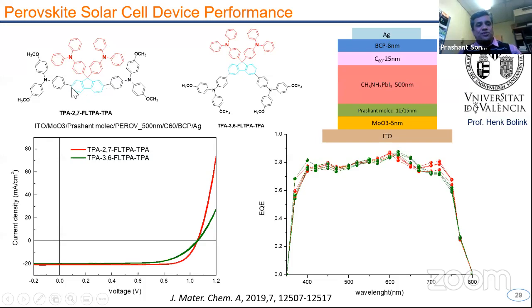Just by changing the position from 2,7 to 3,6, how does the performance change? That was one of the questions we asked ourselves. If we have just a little bit of molecular geometrical change, how can we tune the performance? This time we utilized inverted devices, similar to organic solar cells: ITO coated glass with molybdenum oxide, then our synthesized molecule, then we put methylammonium lead iodide layer, then C60 fullerene as an N-type material, then BCP, another electron transporting layer, and then silver as the top electrode. Molybdenum oxide is a hole transporting layer here.